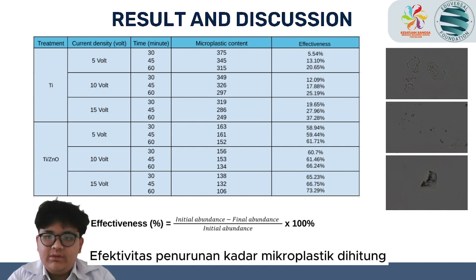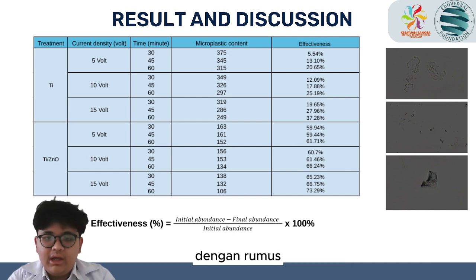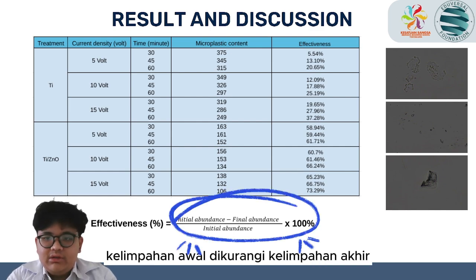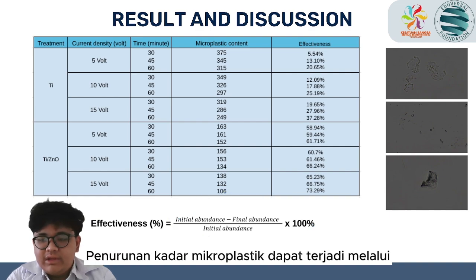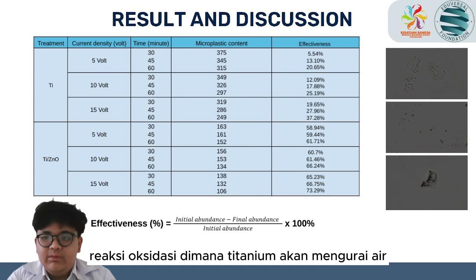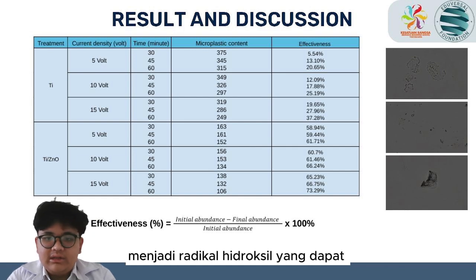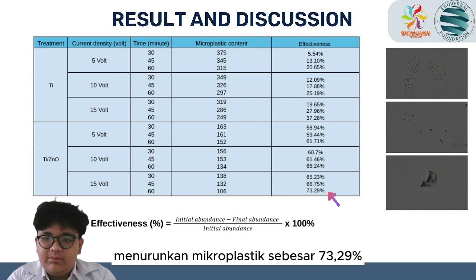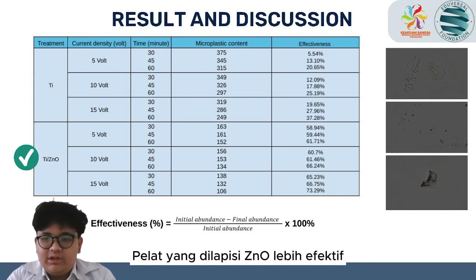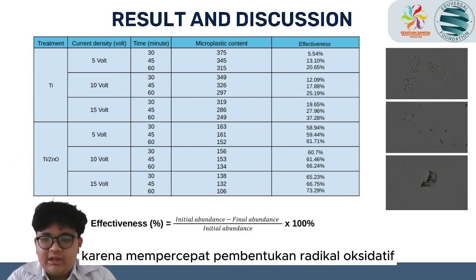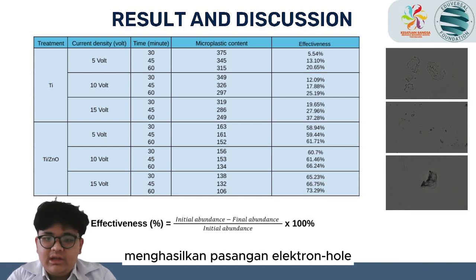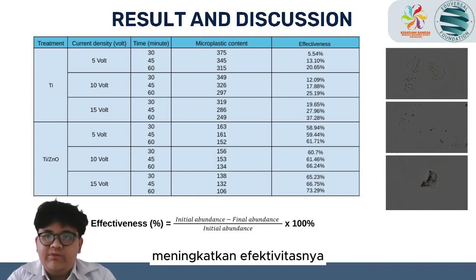The effectiveness of reducing microplastic level is calculated using the formula: initial abundance minus final abundance over initial abundance times 100%. The decrease in microplastic level can occur through oxidation reaction where titanium will break down water into hydroxyl radicals that can break the microplastic polymer chain. Zinc oxide treatment at 15 volt for 60 minutes reduces microplastic by 73.29%. Zinc oxide coated plates outperform uncoated ones by accelerating oxidative radical formation and photocatalyzing light to generate hydroxyl radicals. Higher voltage and longer duration enhance effectiveness.